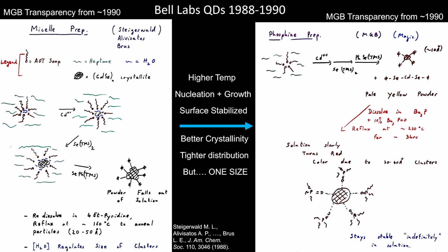So you have a few ions of cadmium, you introduce some selenium, in this case through bis(trimethylsilyl) selenide, which was what Steigerwald knew, all this inorganic chemistry that none of us knew, and that way you made little cadmium selenide crystals inside the water at room temperature. And these are my transparencies from 1990.